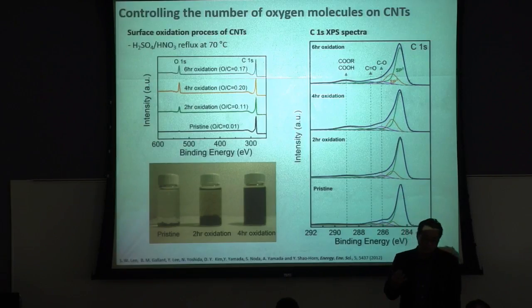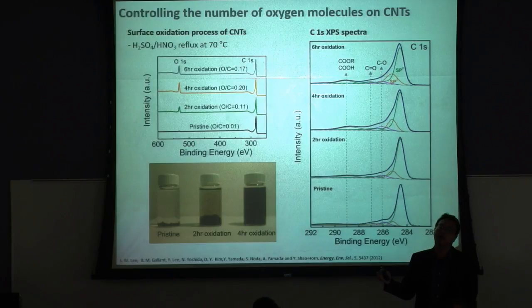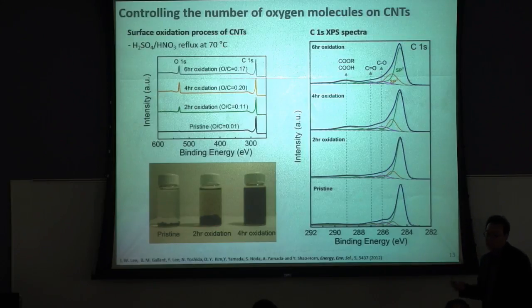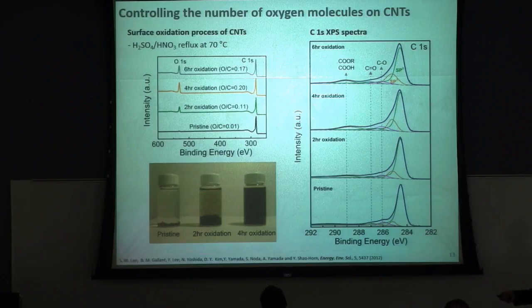Generally, carbon nanotube is very hydrophobic, so when we try to disperse it in water, it agglomerates and quickly precipitates. But if we incorporate oxygen functional groups, the surface becomes hydrophilic. Also, some oxygen functional groups, such as carboxylic acid groups, carry a negative charge on the surface. So we can get a colloidal dispersion, with colloidal stability, if we increase the oxidation time.